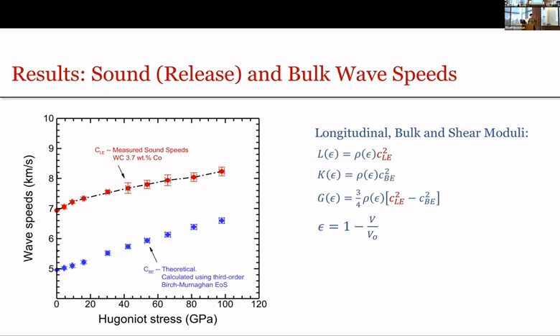And in this figure, the red symbol represents the measured sound speed, and the blue symbol represents the bulk wave speed we obtained using the third order Birch-Murnaghan equation of state. They're all plotted as a function of Hugoniot stress, which is also the longitudinal stress. With those two quantities, we can get the longitudinal, bulk and shear moduli using the relationship on the right.